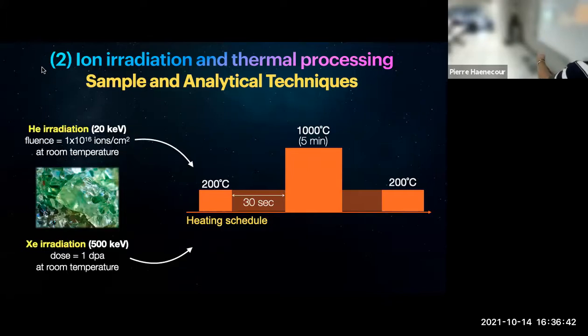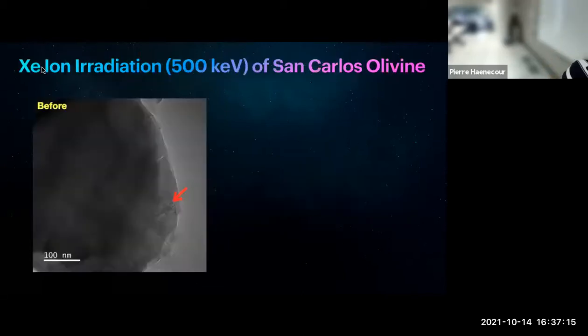Okay, so I'm going to show you two different irradiations we did. We did helium ion implantation using 20 keV helium ions, and then xenon irradiation at much higher energy, to try to see what's happening at different energy with a different type of ion. Then they both followed the same heating regimen, to see if there is any difference between the types of ion compared under the same heating experiment.